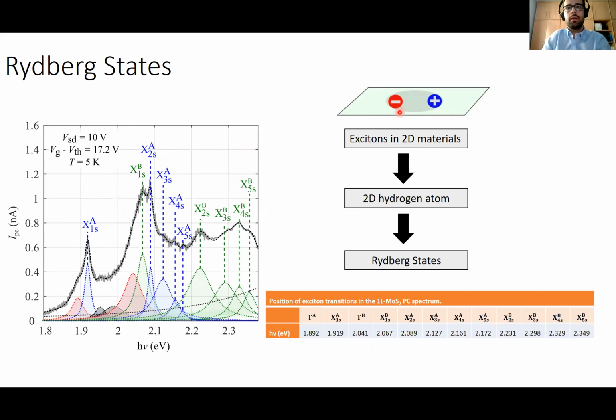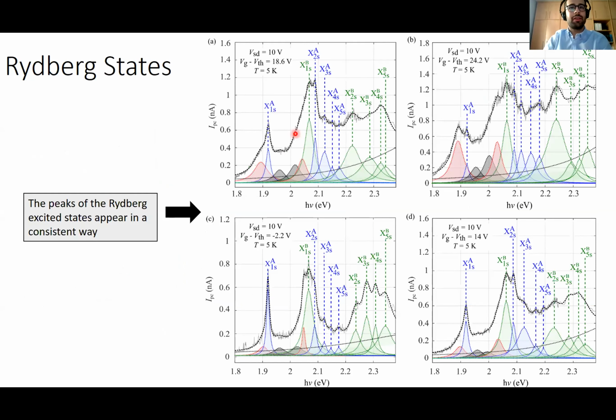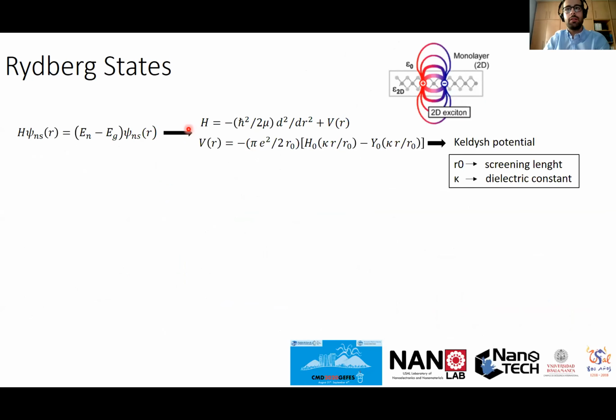We have here the representation of the exciton, and it behaves like a 2D hydrogen atom, and this system has excited states that we call Rydberg states. In order to associate these excited states to the Rydberg states and do a correct labeling of the quantum number, these states appear in a very consistent way in all the measurements. As I was saying, in order to label these Rydberg states, we use an effective mass model, in which we solve the Schrödinger equation with this Hamiltonian, and we use a Keldysh potential.